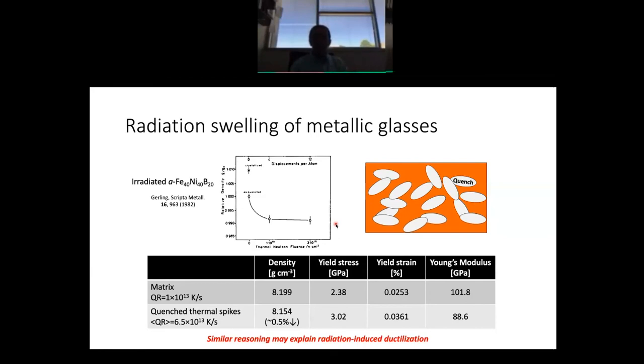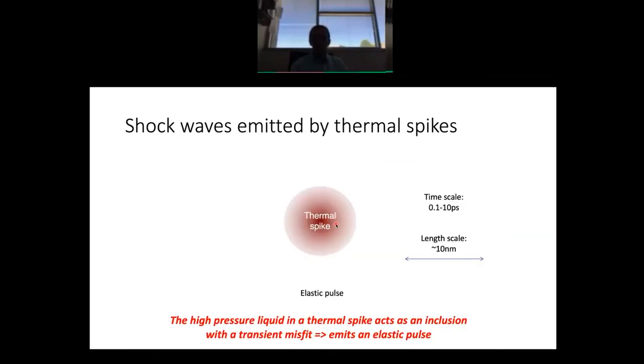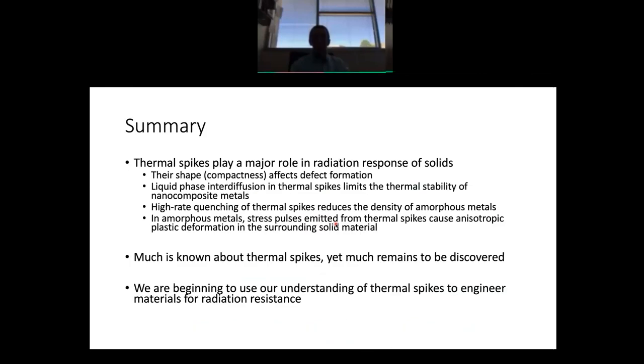Okay, I believe I'm running out of time, so this vignette actually had 2 parts, so I'm going to skip the second part and go directly to my summary. My summary is that thermal spikes play a major role in radiation response of solids, and based on the work that my group has done, I've shown you a couple of examples of how they influence radiation effects. So their shape, in particular, their compactness, can affect the defect formation rates. Liquid phase interdiffusion in thermal spikes limits the thermal stability of nanocomposite metals. But it's also interesting to see that that's only up to a certain critical thickness of the layers. High rate quenching of thermal spikes in amorphous metals reduces the density of those metals.